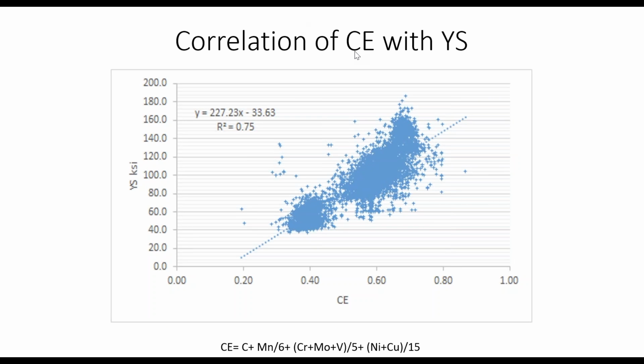Carbon equivalent, of course, is a limitation we put on for weldability. It's also a compositional thing. You can see I actually get a nicer relationship with carbon equivalent rather than DI. I get a 75% correlation, and you can still see the 3 data sets. This is carbon steel, this is the 8600, and this is the 4300.